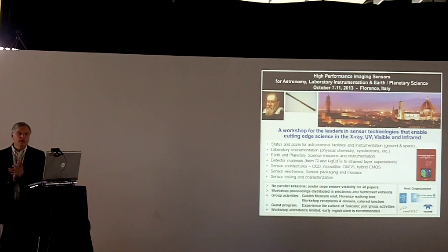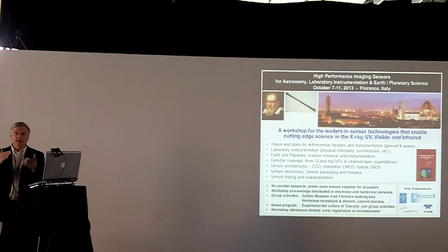Yes. Okay. So the big developments, I think, are things like avalanche photodiodes, and I didn't get a chance to talk here. Mercury cadmium telluride (HgCdTe) is a very manageable material. It's a direct bandgap semiconductor, where silicon's an indirect bandgap semiconductor. And one way of thinking of that means it's extremely efficient at converting photon energy or electron energy to free charge. And so if you get light in, you only need a couple microns thick of the Mercury cadmium telluride (HgCdTe) to absorb all the light. You don't need it 7 to 10 microns.